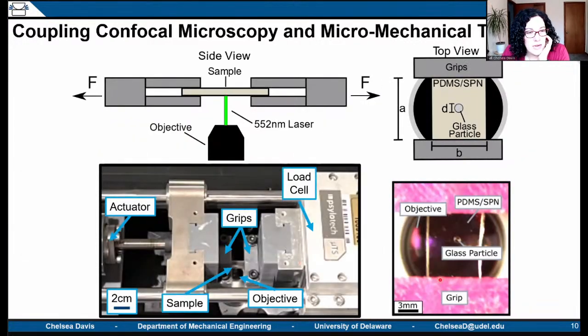So in order to do this, I do want to tell you a little bit more about the system we're using, the mechanics of the experiment. All that we're doing is combining a micromechanical load frame that is going to deform the sample laterally over the objective of a laser scanning confocal microscope. This is what it looks like as a straightforward cartoon, where we have the bead centered over this big circle here as our objective. This is what it looks like when you look down at the microscope, where the particle is about 1 millimeter across, and we can see the objective underneath it. And then here is just an image of the Linkam MT-S that we utilize in order to perform these experiments.